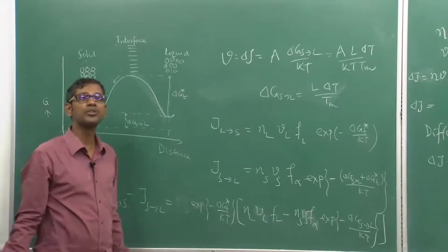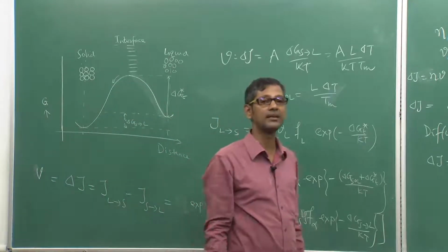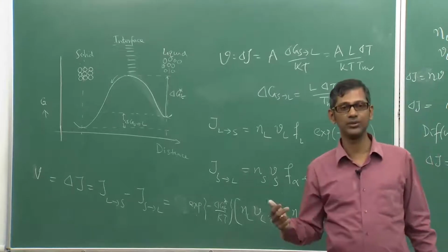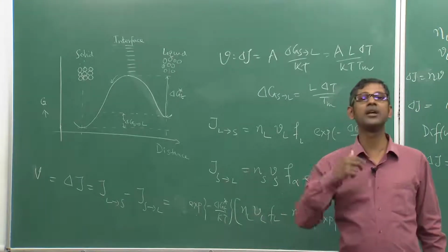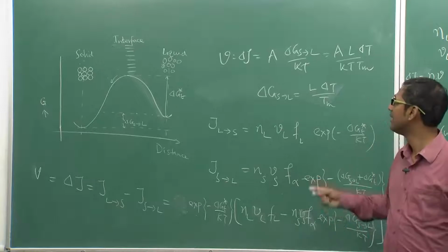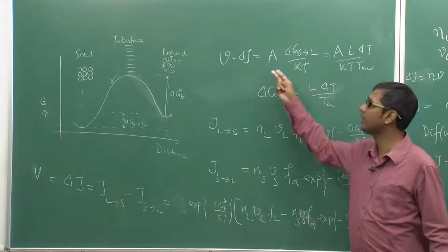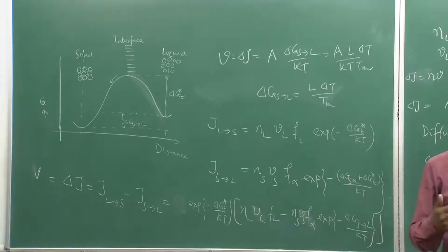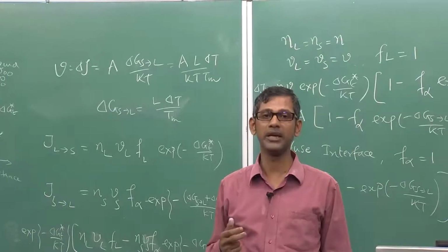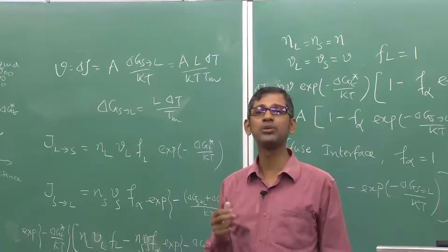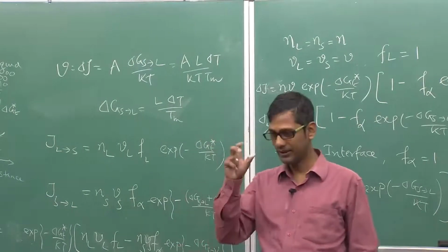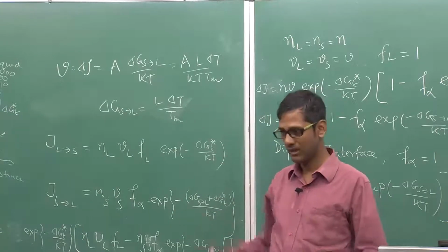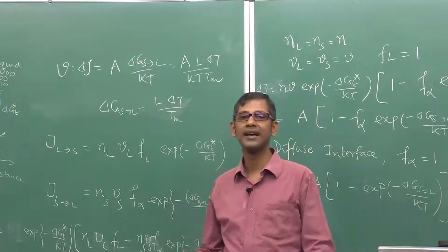And this kind of growth is known as continuous growth in the literature, where atoms will keep on jumping and attaching to the thick solid surface. From the liquid they will jump and attach directly to the solid, and the higher the undercooling, the higher is the velocity. This is only possible in pure metals normally. Let me tell you, pure metals and a few pure ceramic solids, where in a ceramic solid each molecule can easily jump as an object, basically as an entity, and attach to the solid.